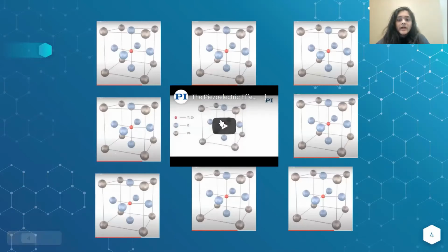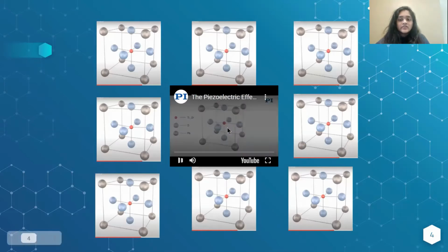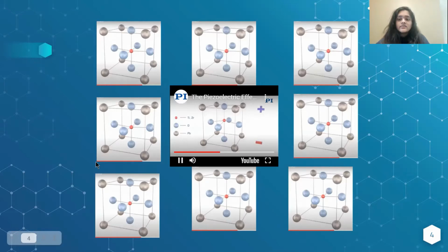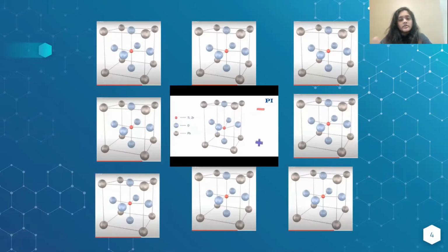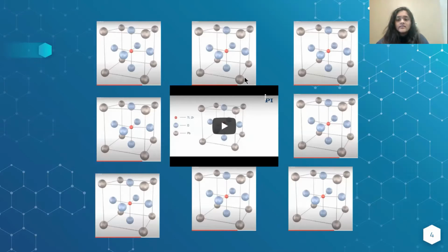So the way that piezoelectricity works is that you have a crystal lattice in which the unit cells remain neutral overall and in balance normally, but when a mechanical force is applied to the crystal, it makes the unit cell disfigure and temporarily polarize. And so that's what you can see here: a force has been applied and the crystal is disfiguring. And so the charge difference caused by the polarization then impacts the unit cell right next to it. And this creates a charge moving through the crystal, which creates a temporary voltage.